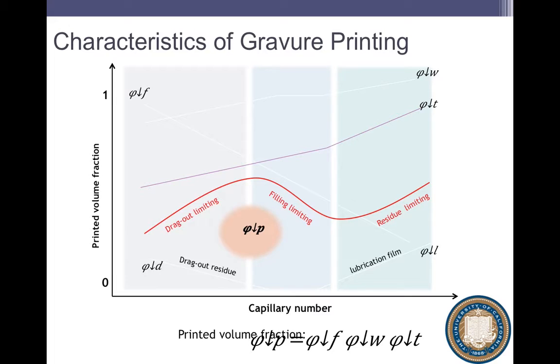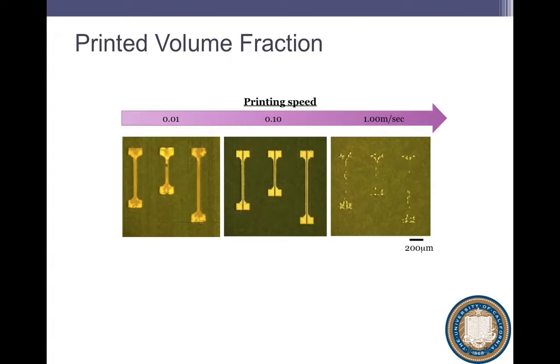Capillary number is related to various things, but the major parameters that affect this are ink viscosity and printing speed. So here's an example of how that works. Now, these are larger features. I'm going to show you state of the art in a minute. But let's say I'm trying to print my source and drain structures, which are these two lines separated by a really narrow gap. Well, if I go too slow, my lines are completely bridged, because the drag-out process pulled ink from the first line and covered the second. If I go too fast, I don't get much pattern because I've trapped air inside the cells. If I go just right, I can do really good lines.